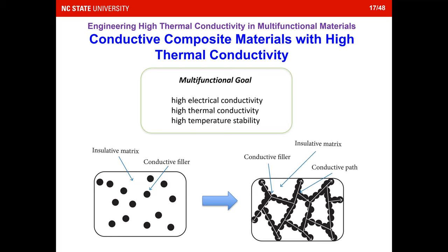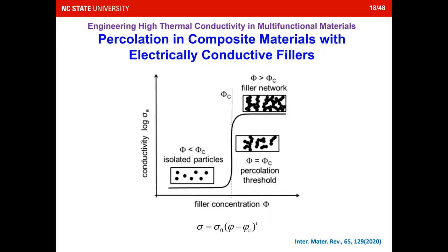And how to beat that volumetric average is by trying to form a network, right? Some conductive paths. So in more accurate terms, this is called percolation, right? So when you start adding different volumetric concentrations of fillers, when the concentration is very small, you have all isolated particles, then the conductivity will be very low. But when you pass a certain so-called percolation threshold, those fillers form a network, then the thermal conductivity and electrical conductivity can be very high. And this phenomenon is called percolation.